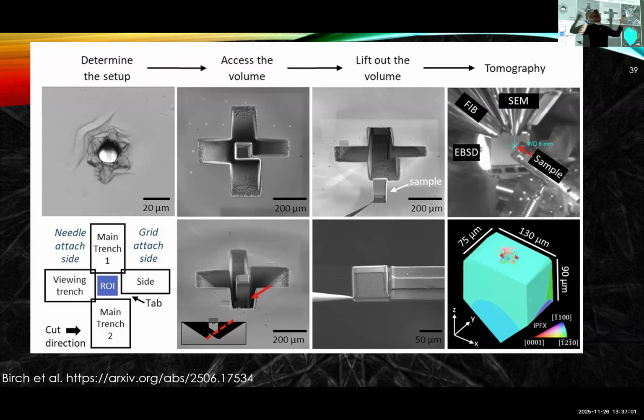What was frustrating, this was a bit of a failed attempt in some regards, because for the indentation, we wanted to have a nice big grain where we were testing the mechanical properties of only that grain. Unfortunately, we found some grains subsurface. So you sort of dug down and found the bedrock, and that was a bit annoying from the mechanical problem, but it shows nicely that you get three-dimensional structures, and we are aiming to publish. We have a preprint in here of all of the prep route to get you here, because that was quite a lot of work to get that to behave.